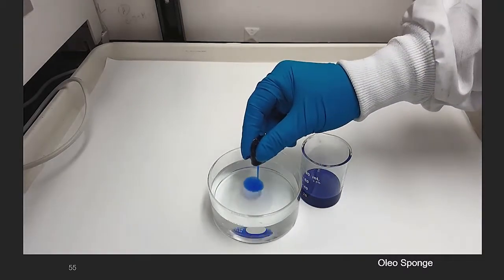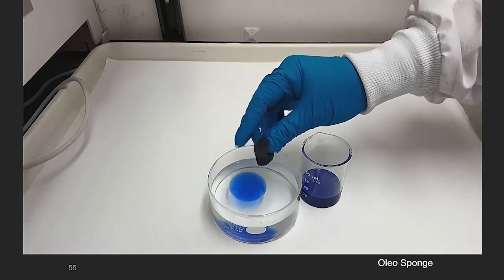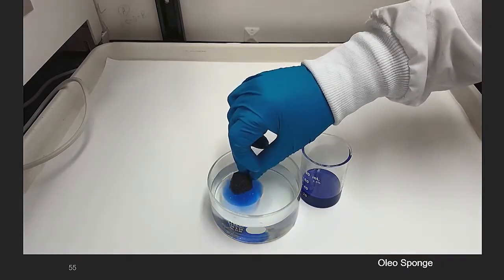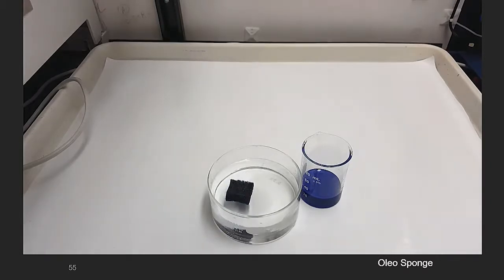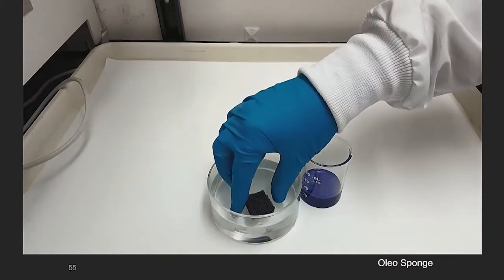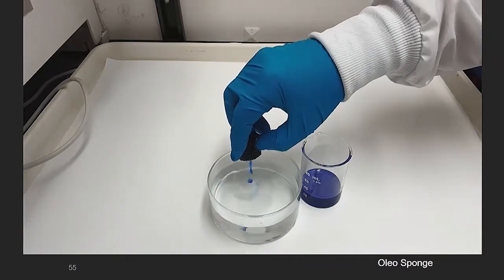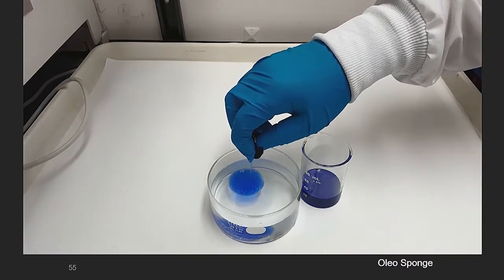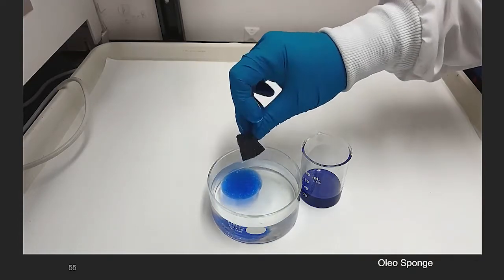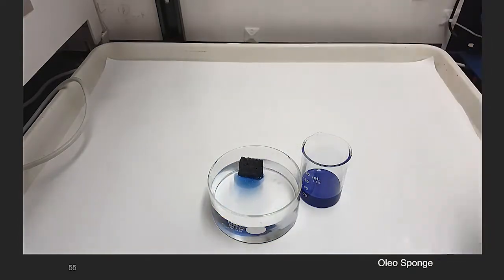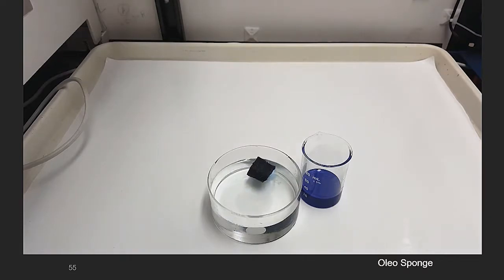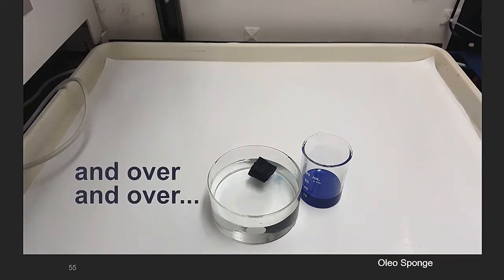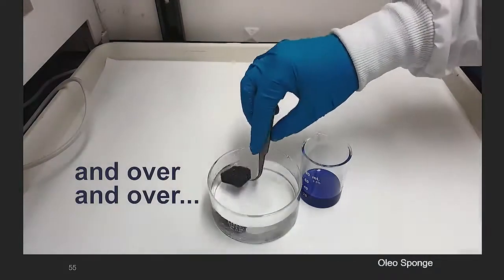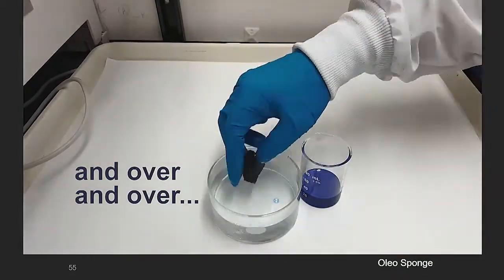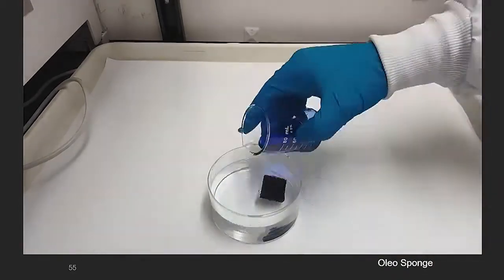And here's an oil spill. Not a very big one, but it's an oil spill. And you'll see what the oleo sponge can do. So it's fast, and it's only grabbing oil. And remember I mentioned you want to be able to recover the oil. There's value in that, right? It's a commodity. So you can actually recover the oil just by squeezing it. And then you can reuse the sorbent. Can just keep doing that. You also notice when he shakes it around, it does not shed oil into the water, which is another important property.